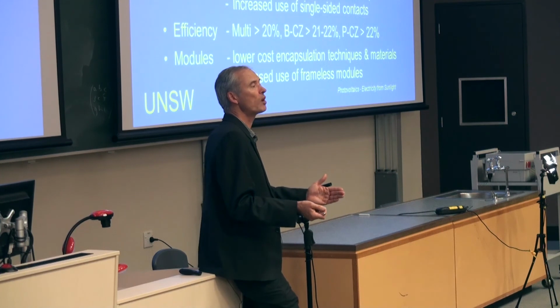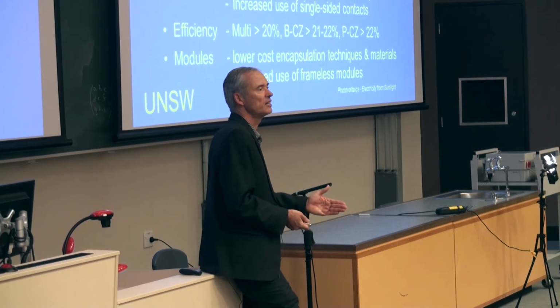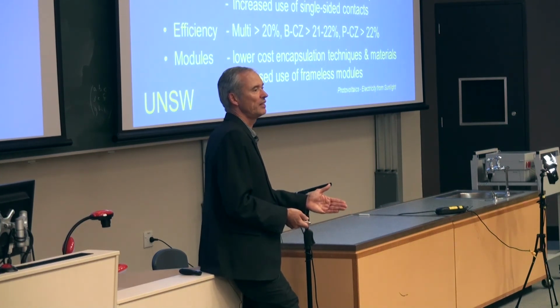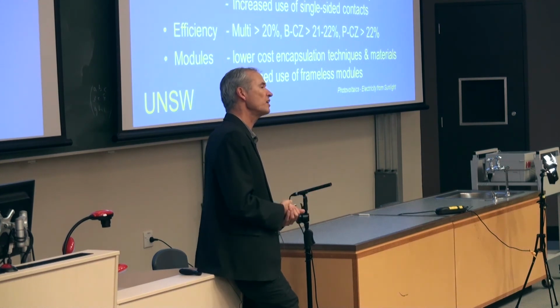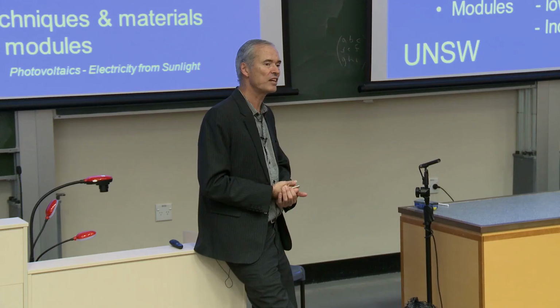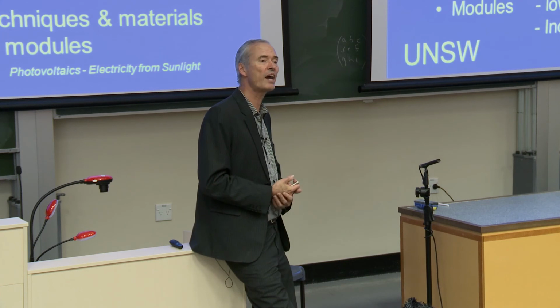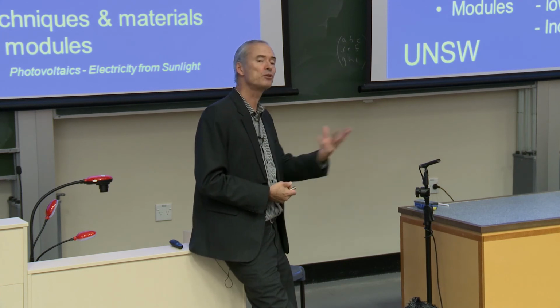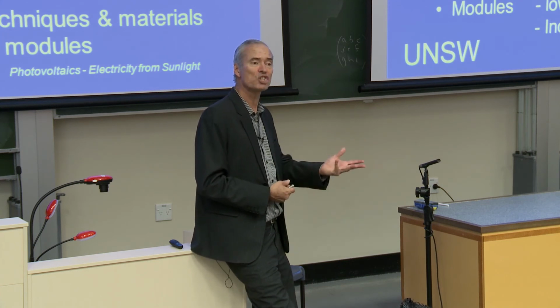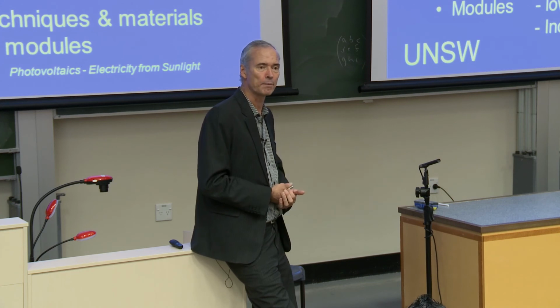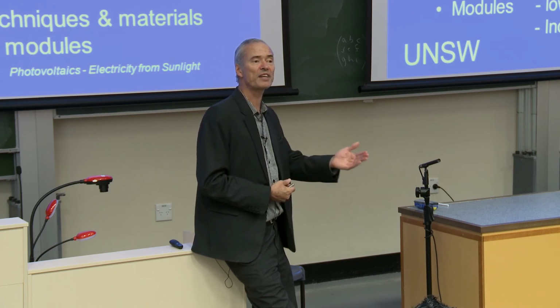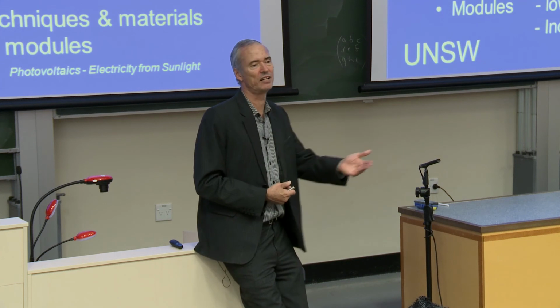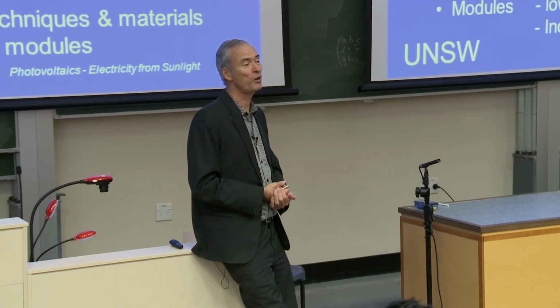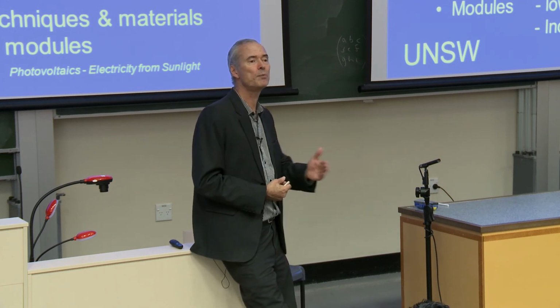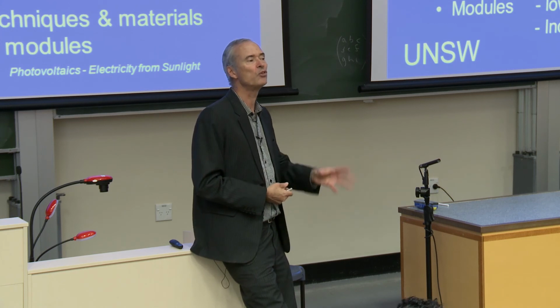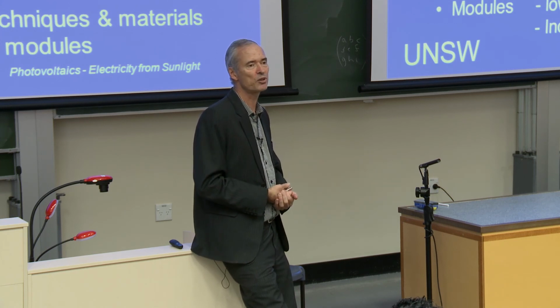But we probably want about 6 nines purity to make good solar cells. Now, you can use some fairly crude techniques to get that sort of purity, and there's quite a few companies around that we're working with that can produce 6 nines purity pretty cheaply, and we call it UMG silicon. Siemens' process, on the other hand, can give you 11 nines purity. The point is we don't need it. For most of the commercial cell technologies, you don't need 11 nines purity.